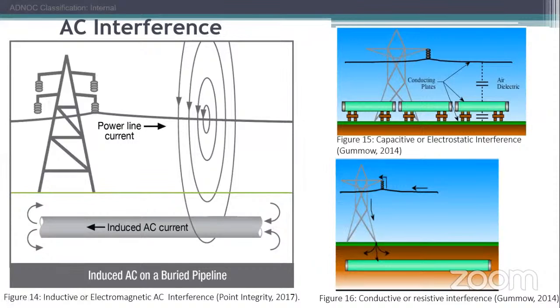Now, conductive is just like when there's a thunder strike. We've seen cases where there's a thunder strike and people get killed even though they're far away from this high voltage transmission line. They get killed because they are probably close to one metallic object. You get? The whole idea is that these high voltage transmission lines may have faults. There may be problems in their foundations, and you find that they are leaking current into the soil. This could also happen due to a sudden strike, thunderstorm, lightning, and the high voltage transmission line introduces current suddenly into the ground. This could also go to the pipeline and could increase the voltage in it.